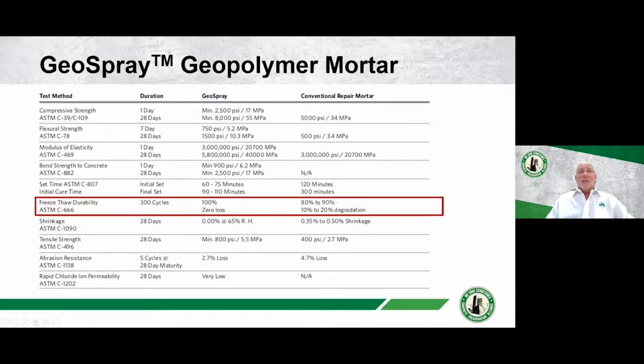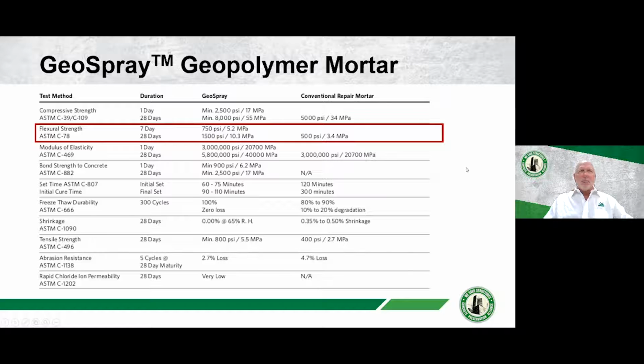So you're going to get, in this case, it shows zero losses using the ASTM C666 test over 300 cycles. So excellent freeze-thaw resistance. But the key feature of the material is the high flexural strength. Because of that tightness, that cross linkage, and the strength of the material, the flexural strength of the geopolymer is up to 3 times more than what you would get with a conventional cementitious repair mortar. And so it makes it ideal for a lining application, particularly a structural lining application where we're relying on that flexural strength for our structural integrity.